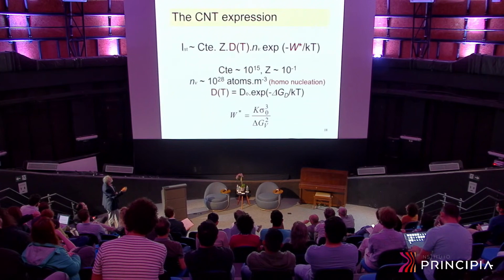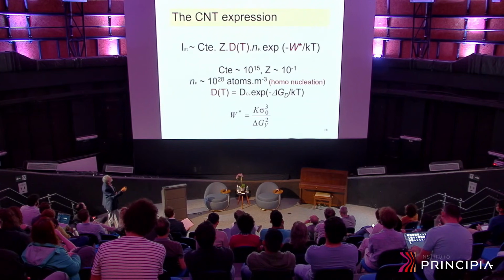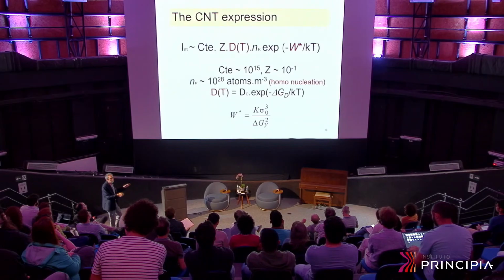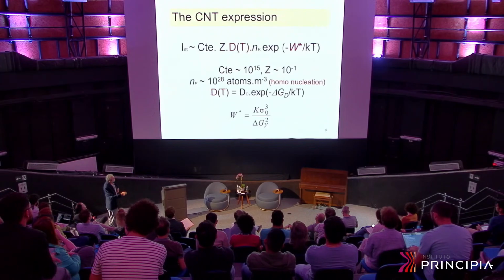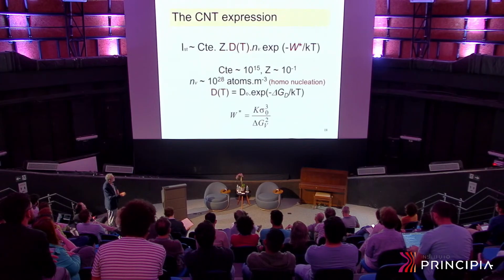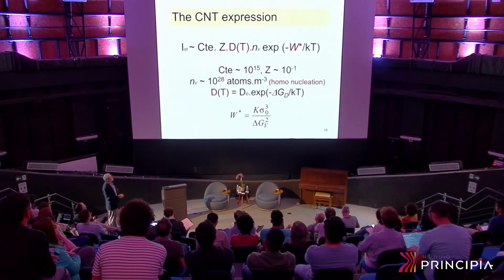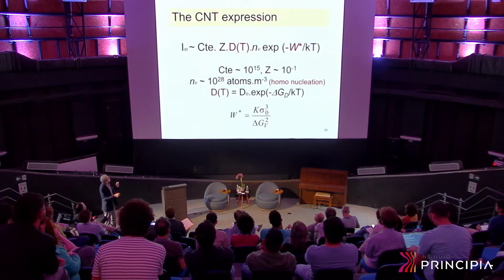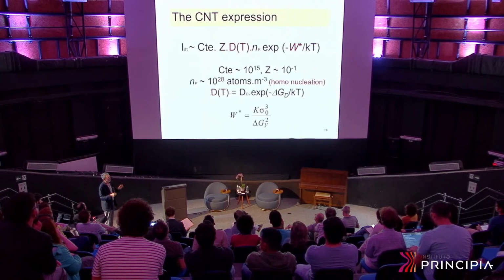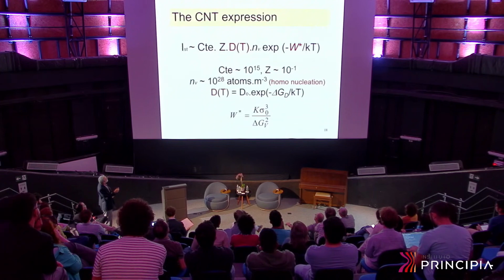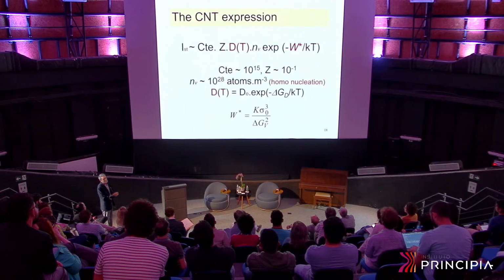It's just the diffusion coefficient in the supercooled liquid, and W star. See, W star is the work for critical nucleus formation from that curve, which is the surface energy to the third power divided by delta G to the second power. And the other things are constants. It doesn't matter at the moment. They're constants that can be calculated. The key properties are the diffusivity and the thermodynamic work for critical nucleus formation.